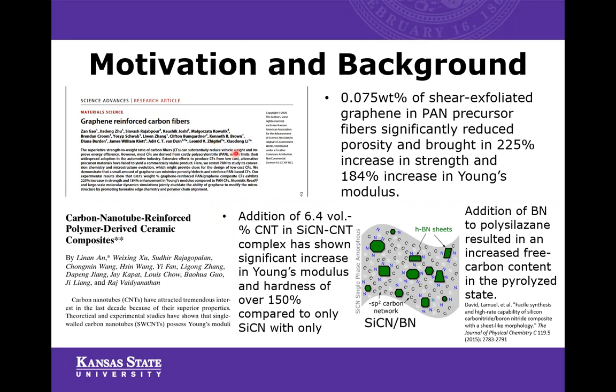More importantly, this work was published only last year and also in Science magazine. Even more importantly, such enhancement was observed at a very low weight loading of graphene, which is 0.075 weight%. Likewise, other kinds of nanomaterials, for example, carbon nanotubes, were introduced into polymer-derived ceramic silicon carbonitride bulk material, which is shown here. And exfoliated boron nitride was also introduced into silicon carbonitride, which was also from our group, which is shown here on the right-hand side.